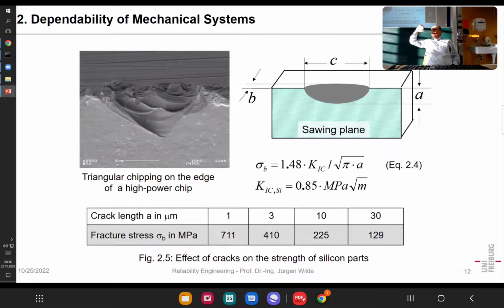So you can say all steels that still can be welded, they have such a strength. If it's a higher strength steel, normally you cannot weld it, so it can go up to 1,500 Newton per square millimeter. So you could say a quite fat person of 150 kilo could hang to that wire of 1 millimeter square. That means diameter of 1.2 millimeter or so. And so that's relatively strong. Now silicon. What is the strength of silicon compared to that?